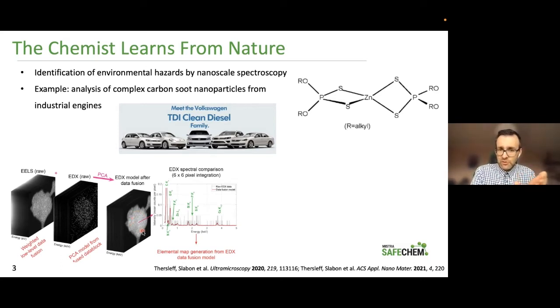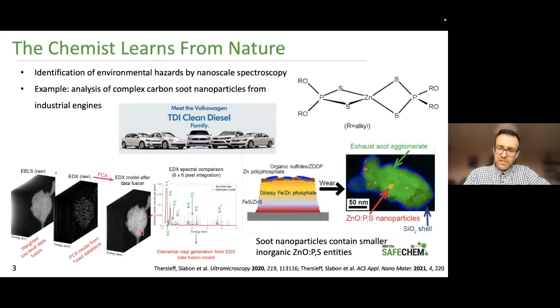You maybe know it from when you change the motor oil of your car. But what we found with a newly developed method using electron microscopy is that actually something else is happening, and we have here a potential hazard. So this kind of polymeric films, they decompose after the end of the usage into such particles of carbon soot, and inside you have much smaller particles of zinc oxide doped with phosphor and sulfur. And this is a potential hazard, actually.